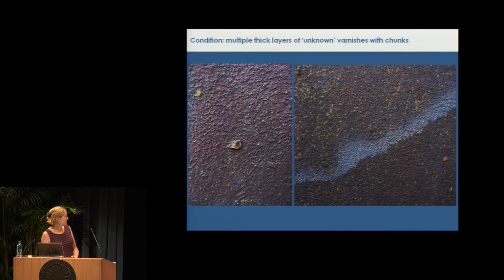So, a closer look at the coating. Here you see 2 close-up pictures of the coating. You have multiple layers, I call it coating, but it's kind of a buildup of multiple layers of coatings that were very badly applied. And you see here on the bottom some brush strokes. Then here you see some chunks of old coating that was mixed with new coating that was reapplied. So it looked pretty bad. And then you have this kind of hazy, kind of water stains, I think. I'm not really sure what they were, but they also made it look very ugly. In some areas, I could measure the coating, and it was about 1/16 of an inch thick.